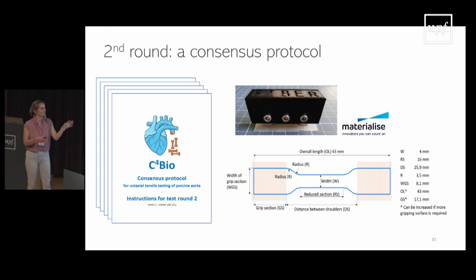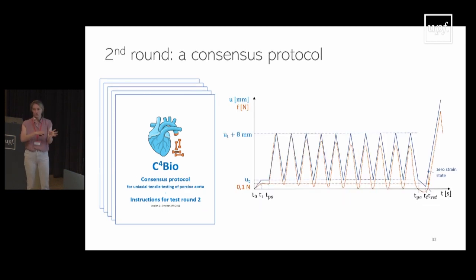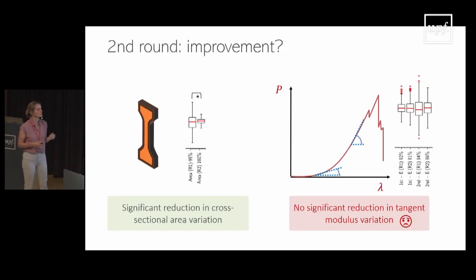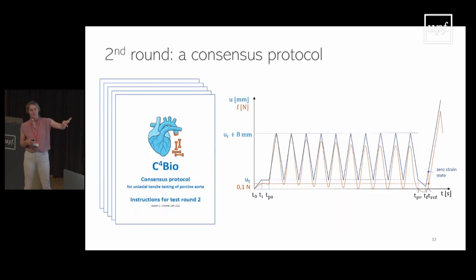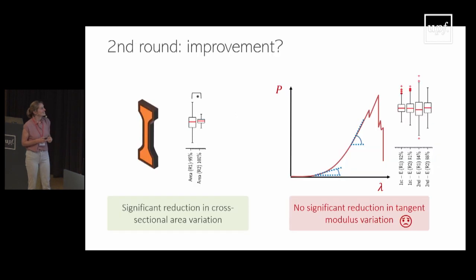We prescribed the shape of the sample. We prescribed the protocol with the preconditioning phase, and we were very clear on how to do marker tracking or digital image correlation. So we were very confident that this time we would get it right. And well, a bit of good news, let's say: the surface area of the samples, the research group variability there was significantly reduced. But I mean, if we wouldn't even have managed that when everybody got the same cutting tool, well, then we should have all just gone home.